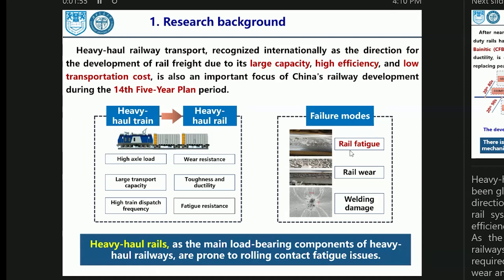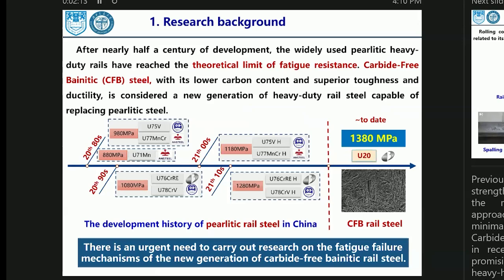However, the mechanical properties of the rail steels currently in service in China fall short of meeting the increasingly demanding operational conditions. We need to find another choice, for the currently used pearlitic heavy haul rails have reached the theoretical limitation of fatigue resistance, and the carbide-free bainitic steel, due to its low carbon content, has good structural toughness and ductility. So this material is considered a new generation of heavy haul rail steel.